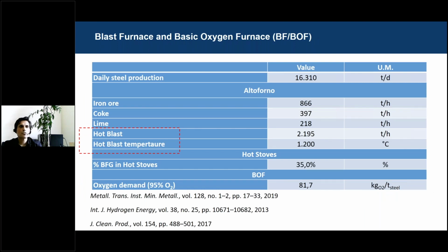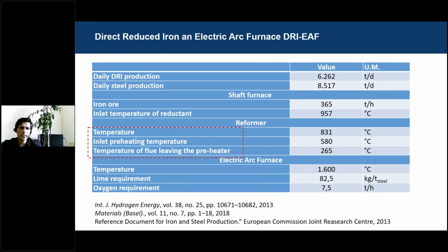Here I report, just for your information, the main parameters used in our simulation. We see iron ore, coke, lime, which we have taken from this reference. Here I report also the hot blast. The hot blast refers to the preheating of air blown directly to the blast furnaces. Part of the blast furnace gas leaving the steel mill is used to preheat the air along with some request of methane.